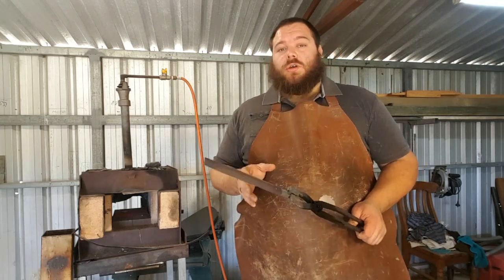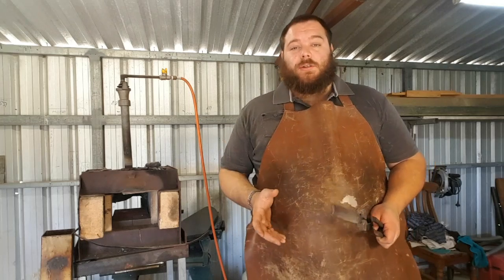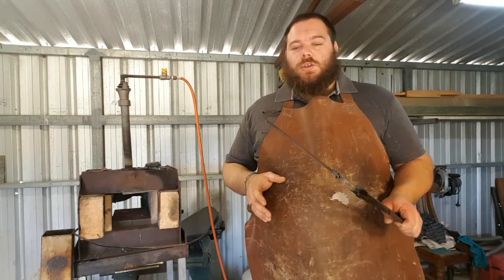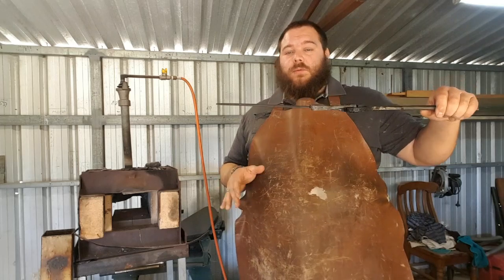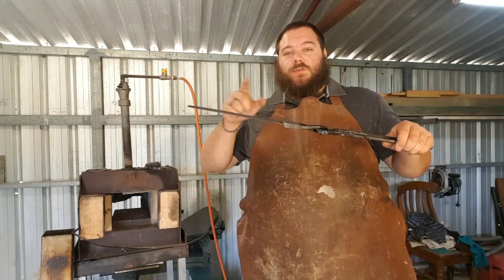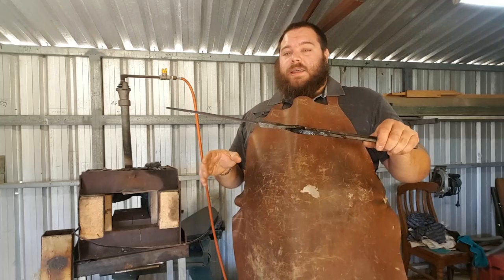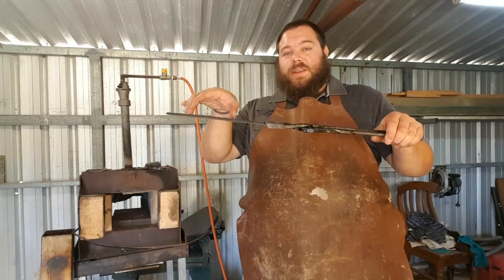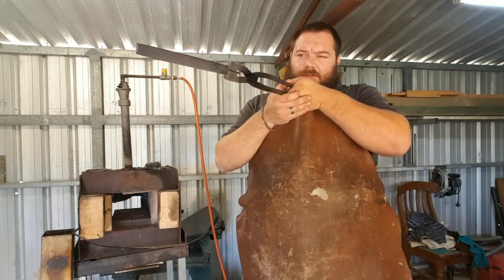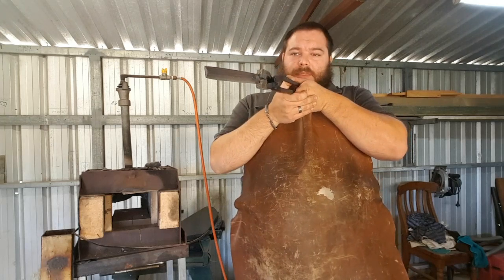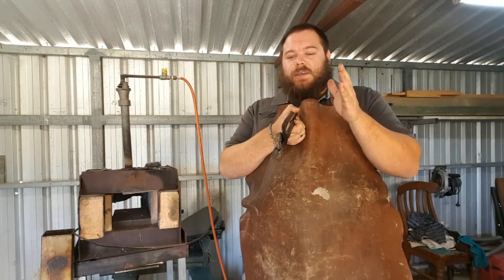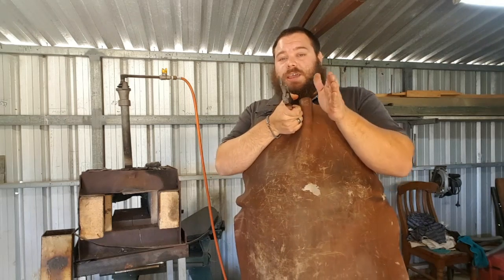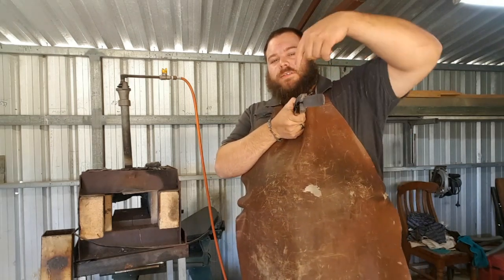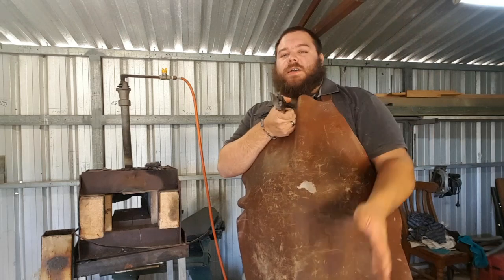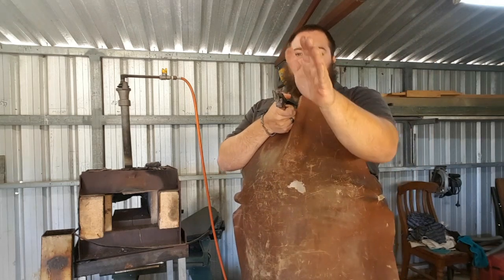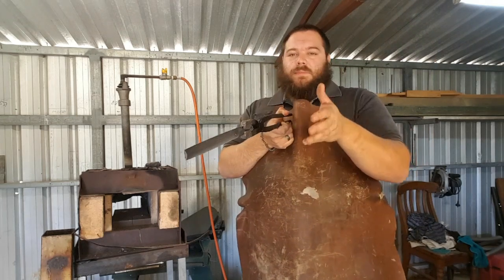What you don't want to do is put it on a cool surface like your anvil. If your anvil is nice and cold and you put a piece of flat steel on there, this side's going to cool faster than this side, and it's going to contract, and you're going to end up with a banana for a piece of steel, even though you haven't quenched it. Because this is a half-round file, it actually has warped somewhat, because the big flat side is cooling faster in the air than the round side is. And that's something to be careful of.